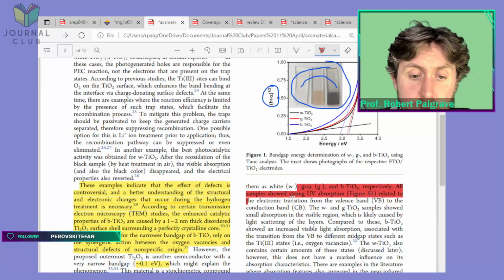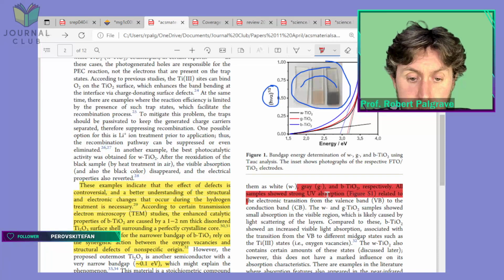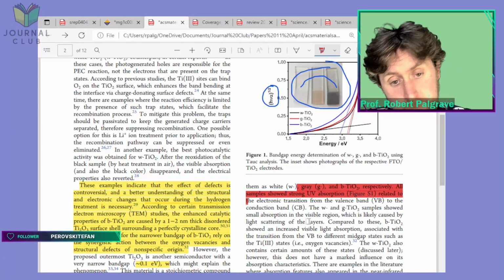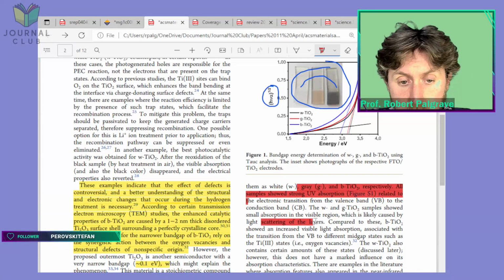Anyway, the electronic transition from valence band to conduction band, this is the absorption edge here. The W and G TiO2 samples, so the white and the grey ones, showed small absorption in the visible region, which is likely caused by light scattering off the layers. That's just kind of what I just said.